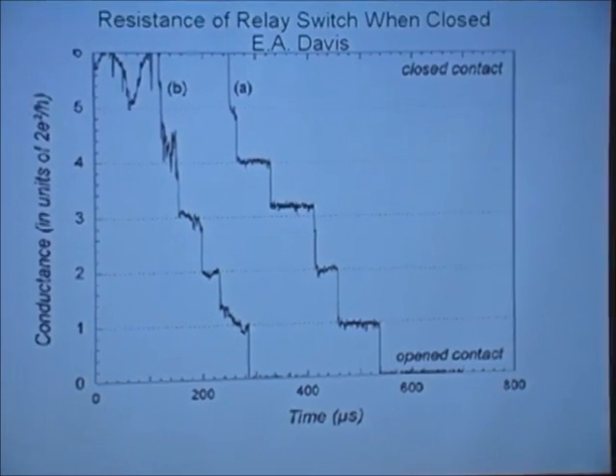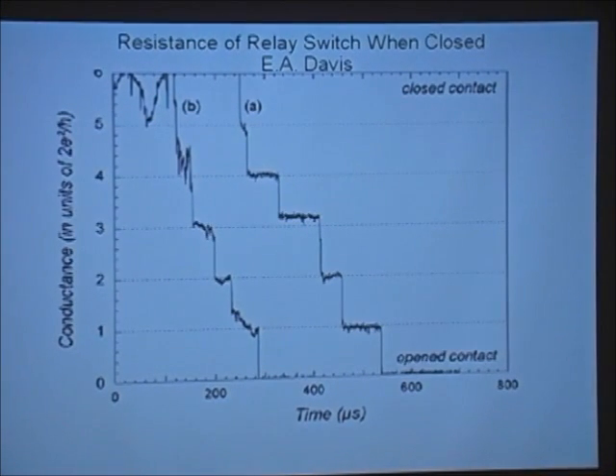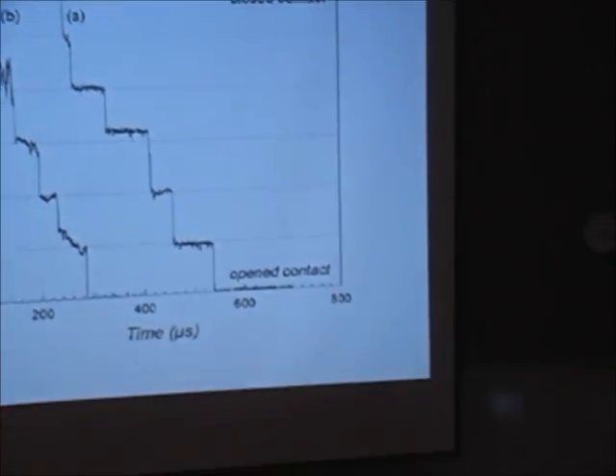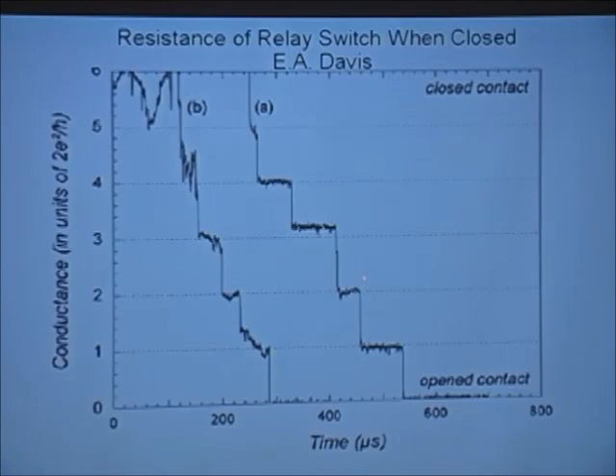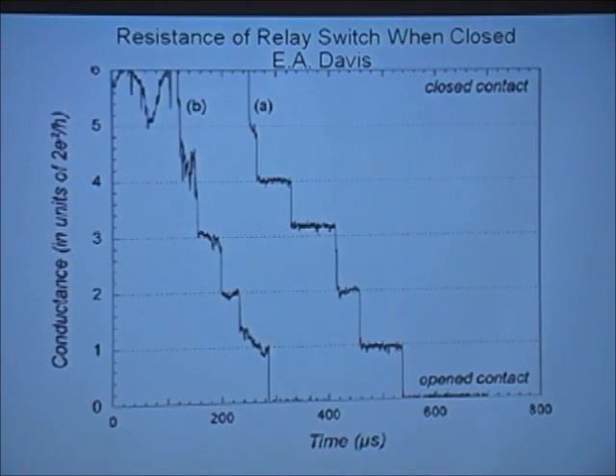Ted Davis at Leicester University set up a teaching lab experiment in which he took a relay switch, just an ordinary brass switch. You just tap it to make a contact. As it comes down like that, the first contact is 1 atom wide, 2, 3, and so on. And when it comes away, you get 4 atoms wide, 3, 2, 1, 0, and so on. So this is what it looks like. This is just a standard metal switch. You're tapping it, measuring as a function of time, and you see here a quantized conductance. So it's fairly widely observed. This, of course, is room temperature.